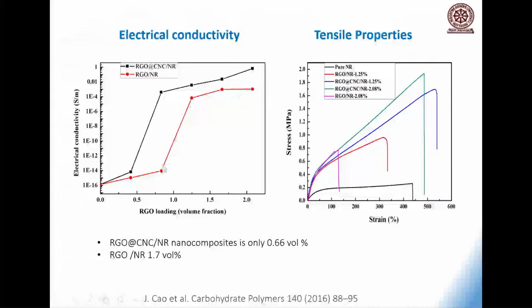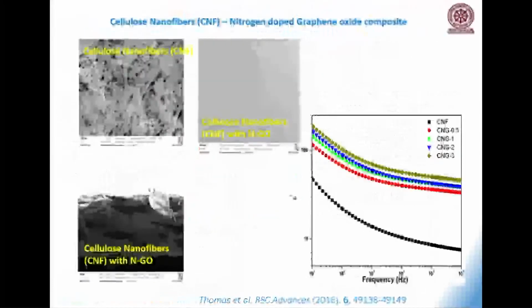You see a percolation process. The black is reduced graphene oxide and nanocellulose in natural rubber. You can see the percolation shifted to lower concentration of reduced graphene oxide. So message is, you can mix nanocellulose with several conductive fillers. It could be CNT, it could be RGO, and you can make beautiful sensors.